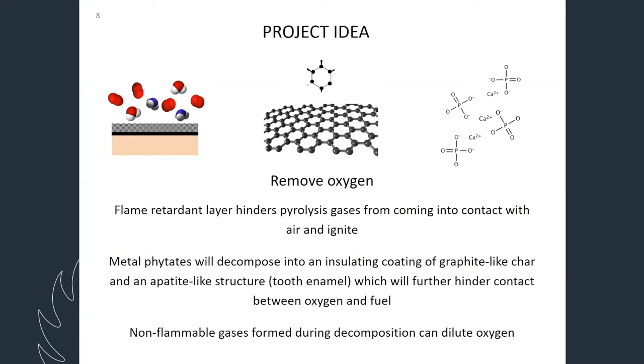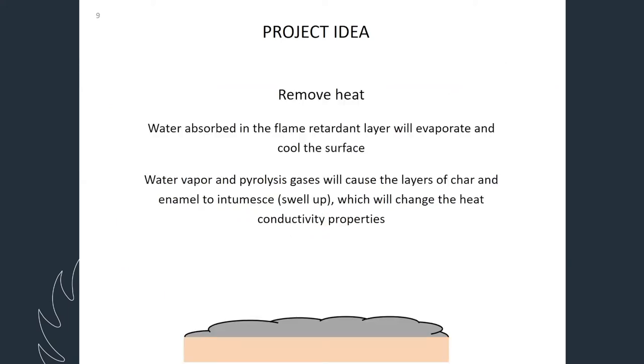And the phosphate groups that are left and the metal ions, for instance calcium, will form an apatite-like structure, one type of calcium phosphate that is the same as we have in our tooth enamel. So this will be a very hard barrier, which will then hinder the contact between oxygen and fuel. And depending on how we mix those components of the flame retardant, we can also get non-flammable gases that can form during the decomposition, which can then dilute the oxygen so we don't reach the lower flammability limit.